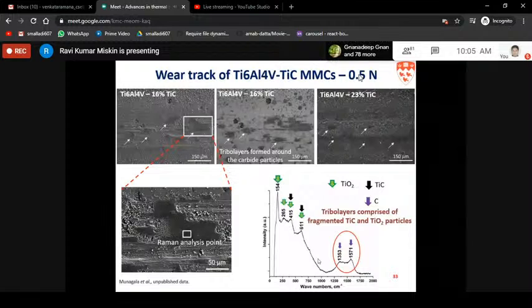These protective layers were not formed in case of pure titanium 64 coating. And when you increase the titanium carbide content to 23%, these layers are more continuous on the wear track, which means that your titanium carbide particles are facilitating the formation of these hard tribofilms. When we did Raman analysis on these tribofilms, we found that apart from titanium oxide and carbide, we could see free carbon. That free carbon was the free carbon that we had in the particle. So what is the advantage of free carbon? Can you go to the next slide?